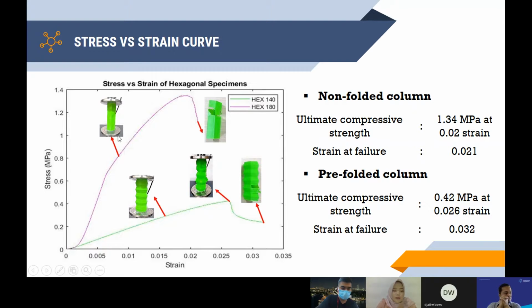The purple curve is the stress strain curve of the non-folded thin-walled column, while the green curve is the stress strain curve of the pre-folded thin-walled column. For the non-folded column, the stress quickly increases with the strain until the compressive strength at 0.02 strain, and then significantly drops, then fractures at 0.021 strain. From here, we can say that the column is a brittle material because it breaks at lower strain.